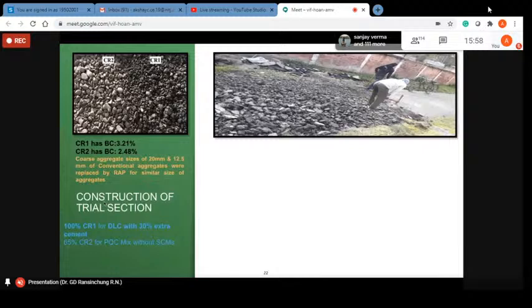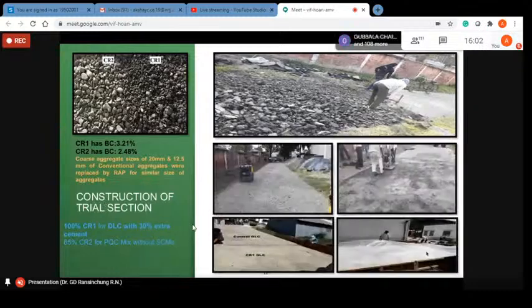The difference between the DLC layer of the conventional mix and the concrete mix prepared with the RAP material is shown here. And by appearance, by visual inspection, there is no difference at all. On top of this DLC layer, a separation membrane, 125 micron thick, is provided. This is sandwiched between the DLC layer and the PQC layer to act as an anti-frictional layer.